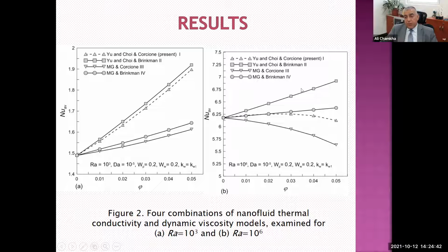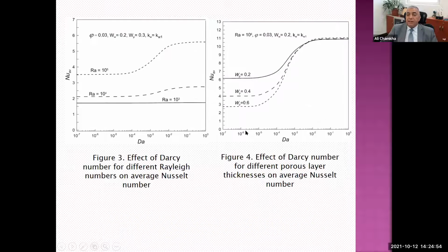you'll see again the reduction that we saw in the Yu and Choi model in the simple problem we showed. So again, I wanted to show here that it's not always the case that when you increase the volume fraction of nanoparticles, you have enhancement of heat transfer. It depends on the model you're using. And here it raises a big question: what type of model should we use? Which is more accurate? Which is the correct one? That's something left to be done in modeling nanoparticles and nanofluids.